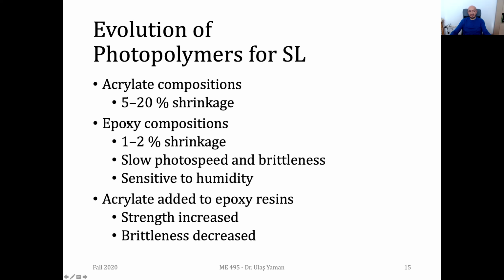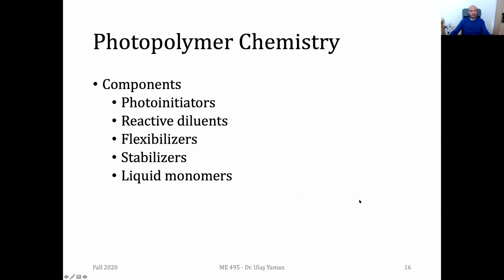And later, they joined these acrylate compositions with epoxy compositions, and they were quite successful. The strength of the products is improved, and also the problem of the epoxy composition is eliminated. Right now, the brittleness is decreased to very low levels, and with this new composition, having acrylates inside epoxy compositions results in a good composition, and we can use it in our stereolithography or in our printing processes.